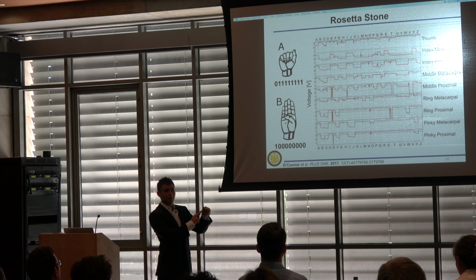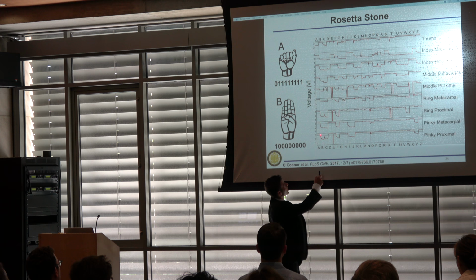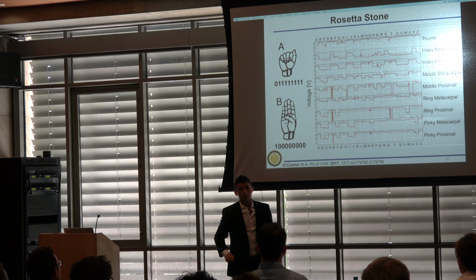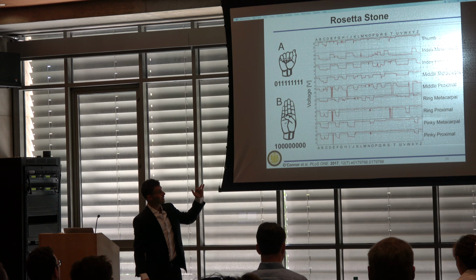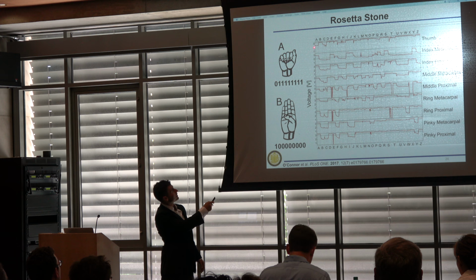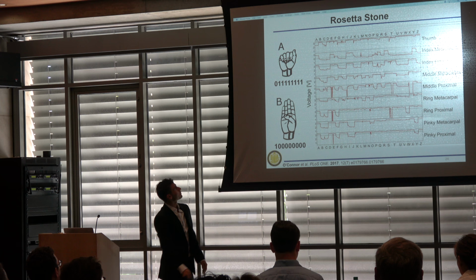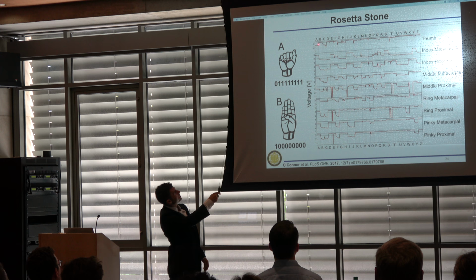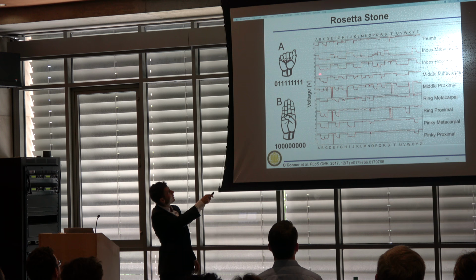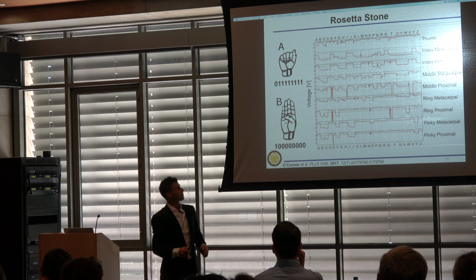And it may be a bit hard to see in the back, but there are dotted lines that run across each trace. If the voltage signal is below that of the red line, it will assign a 0. If it's above the dotted line, it will be given a 1. So A should be below the dotted line here, as it is, and then all the rest are above it. And now, conveniently, B is the exact opposite key. So what we see is the trace has now jumped up. It's now above the threshold value, so it's assigned a 1, and all the rest of the signals have dropped down, below. So as each finger was relaxed, the resistance across the sensor dropped.